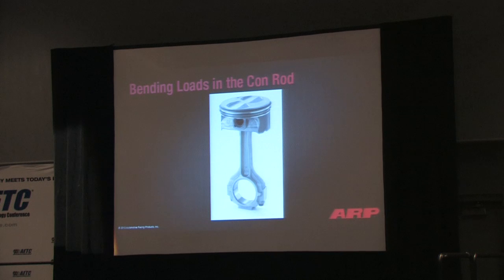So if you were to take an O-ring and hold it in your fingers, and you put your fingers in the top and the bottom, as you pull this way, it pulls the sides of the O-ring in. That's exactly what's going on in the connecting rod. So there's a bending load that pulls the joint on the mains journal here towards the journal of the crank. Obviously, there's only so much clearance in there because of the oil clearance between the bearing and the journal. So it's a very small amount, but it is significant in that you've got a bending load going on that bolt. So the bolt is basically being bent in this direction every cycle.